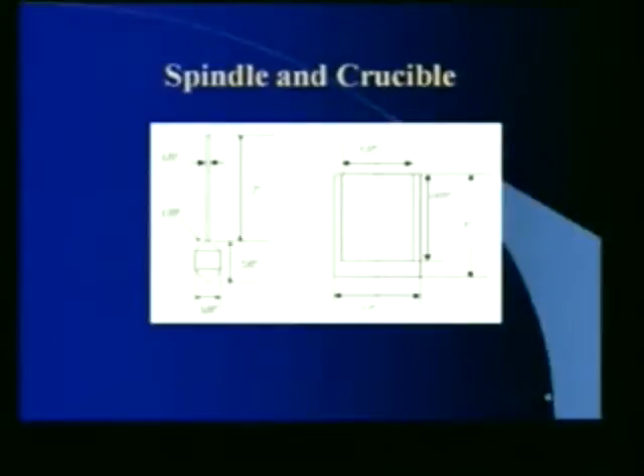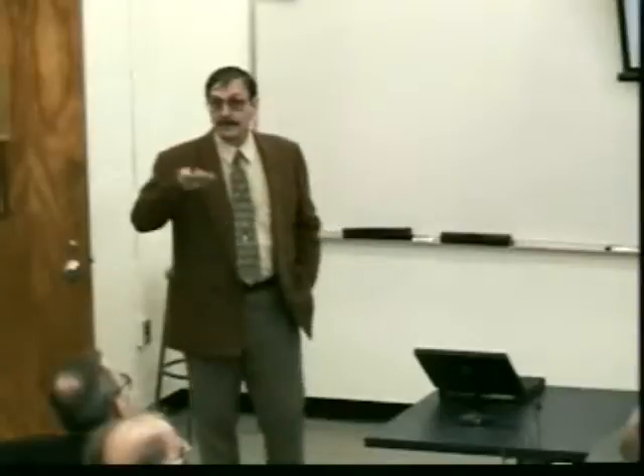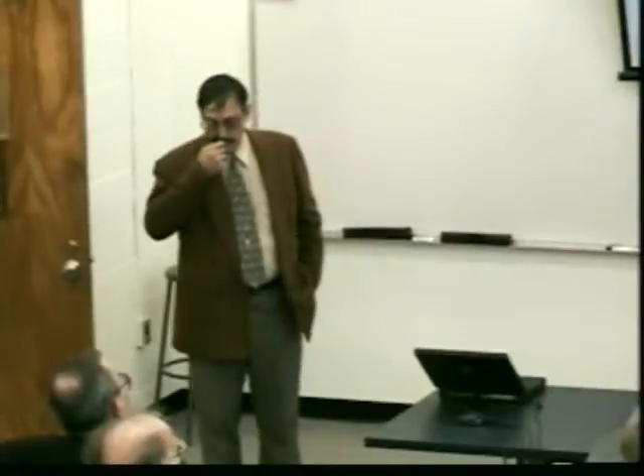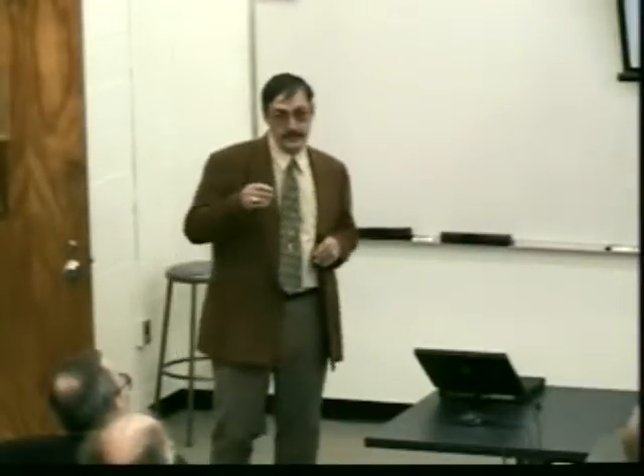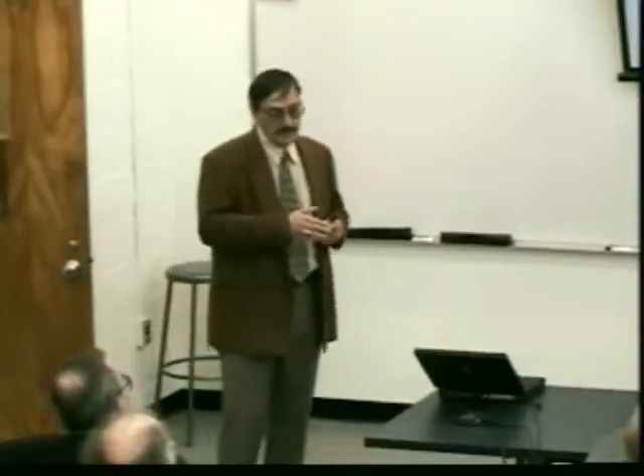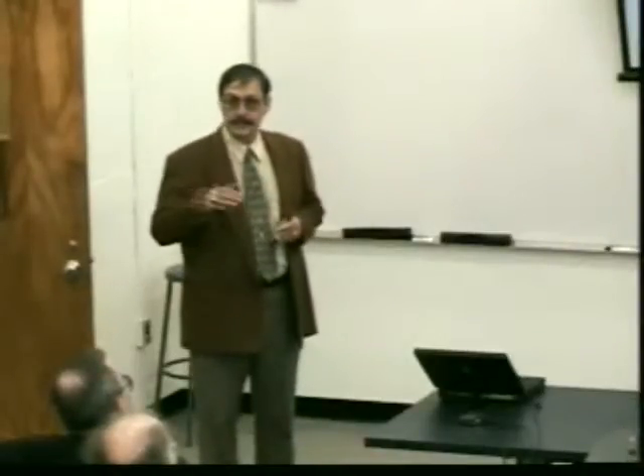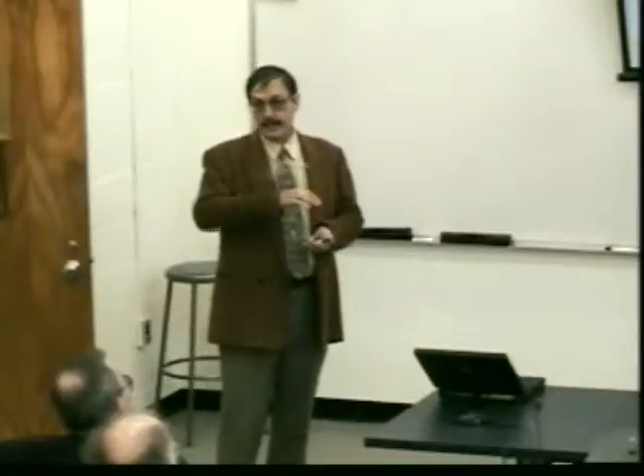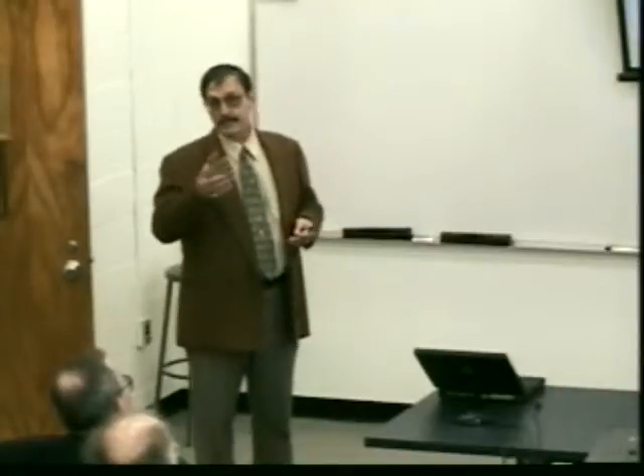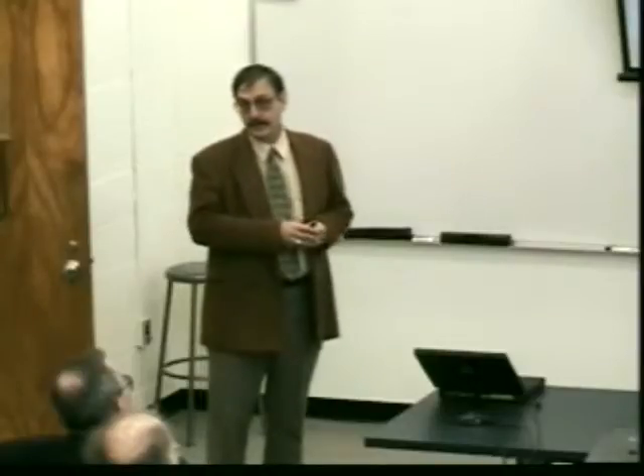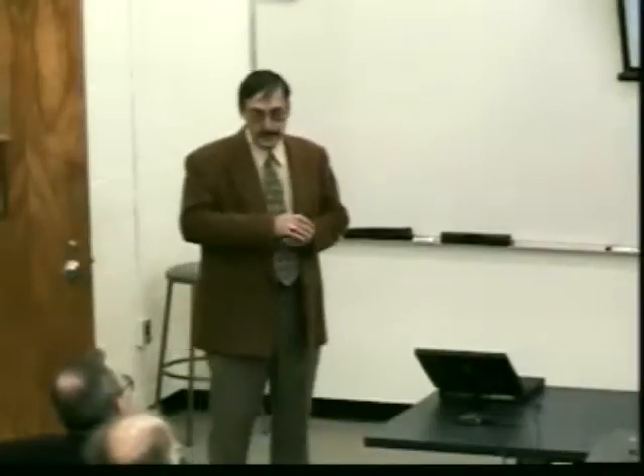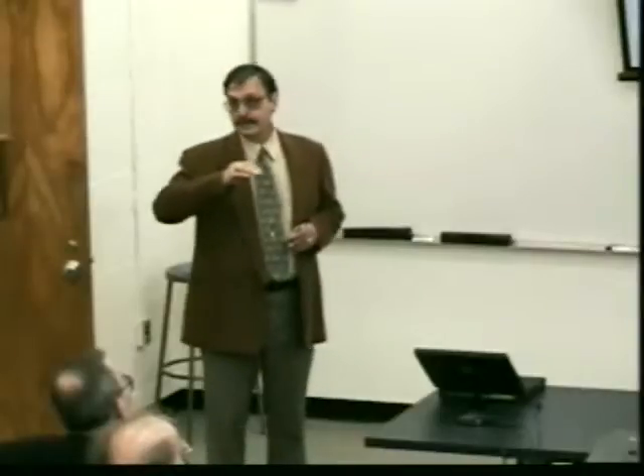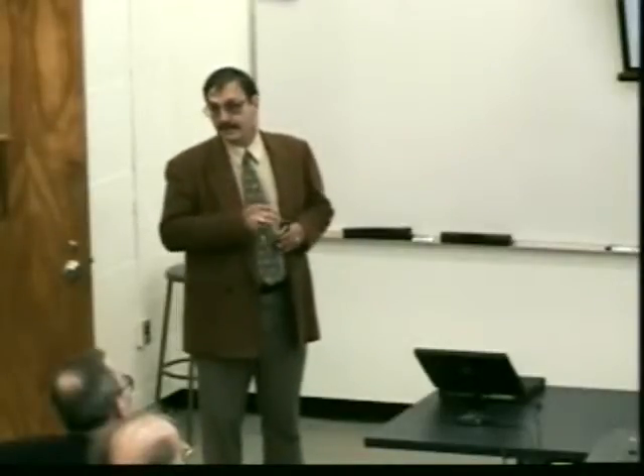That basically amounts to a spindle, and you use a viscometer and rotate, and a crucible, and this just shows a general design. What these are made out of is a very difficult problem, particularly when you're looking at very high temperature measurements. You may ask, well, why high temperature measurements? Well, a lot of the newer vitrification technology involves the use of thermal plasma and use glasses which potentially can have a much higher melting point or much different conditions than conventional borosilicate glasses. So we'd like to be able to determine some of these properties at elevated temperatures to see if some of these new technologies have some viability.